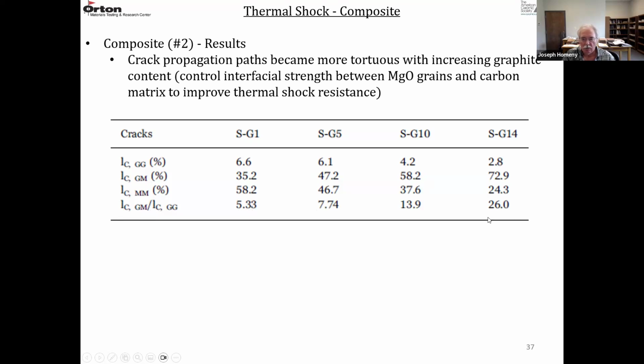So what is that telling you? In the high graphite content material, the interface is real important. So you can try to control the interfacial strength between the MgO grains and the carbon to improve the thermal shock resistance. So that's one of the key findings here, is that you want to control that strength, because that's the main crack propagation path. So if you have a very strong interfacial strength between the matrix and the MgO grains, that path is not going to be that active. If you have a weaker interface, that fracture path will be more active. So you want to control that interfacial strength.